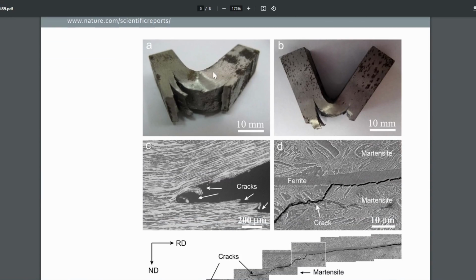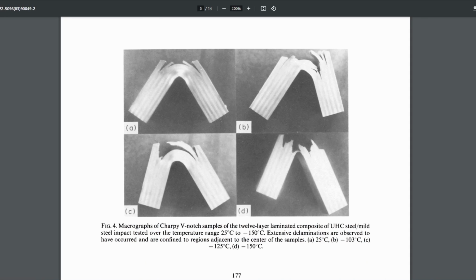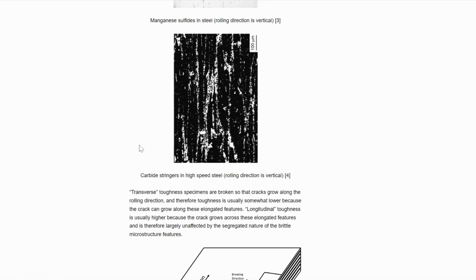And then they break it so that the fracture goes through the layers, and that leads to a fracture that has to cross through the soft phases, and that leads to higher impact energy. Now, this is actually something I almost covered in one of my Damascus videos, because they have done studies where they've taken high carbon steel and low carbon steel and laminated it together and then broken them across the layers, and it does lead to higher toughness. Now, this doesn't always lead to a benefit.